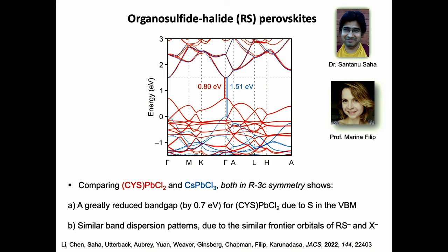So here's a real band structure if you're curious. And I won't go through all these details, except simply to say that by replacing one chloride with sulfur, I have essentially replicated the band structure of the chloride perovskite, except that I have moved all the filled states up by 0.7 eV. So that's a lot. So we can maintain the highly desirable band structure of the halide perovskites, but just make the band gap smaller by using sulfur.